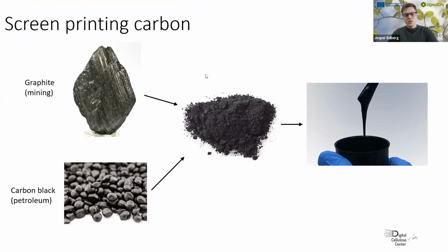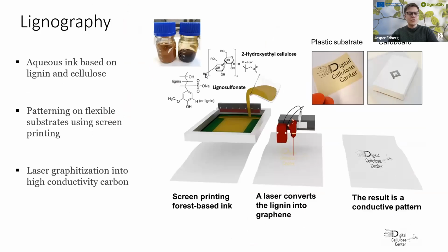So we wanted to see if we could combine these three things using forest-based materials, using laser graphitization, and combine this with printed electronics. And we did this by formulating a printable lignin ink, which we then could coat using printed electronics. And then we applied the laser on top of this to turn the lignin ink into conductive carbon.